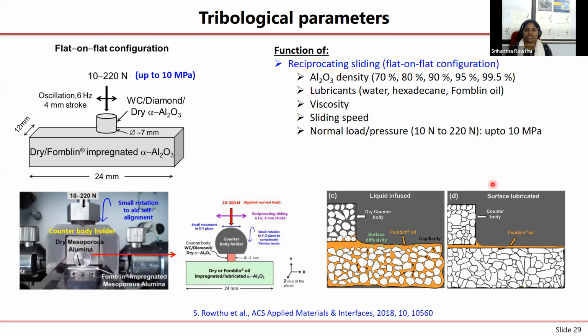Okay, so here, if you have your substrate to be a porous material, then it is called a lubricant infused or impregnated situation, because it's actually getting infused. If it is a fully dense specimen, like 95 or 99.5%. Why did I say 95 as fully dense? Because it has predominantly closed porosity, but not open porosity. And obviously the liquid cannot enter into your closed porosity.